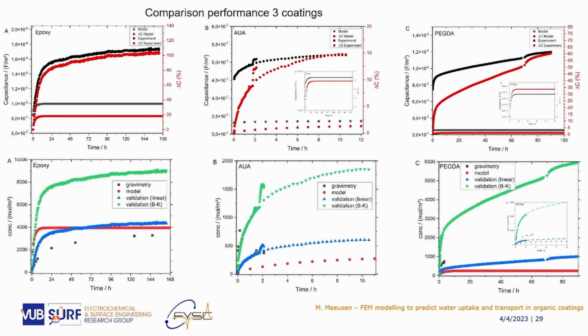But here you start to have a discussion about the impedance measurements, because the water uptake is based on the change of the dielectric constants. And there is a systematic discrepancy, also published in the literature, between gravimetry and the impedance data. At the moment, we take into account the swelling. We start to look, for example, at the ionic strength of the water because it is influencing the water uptake. So it is quite complicated to compare the two systems.